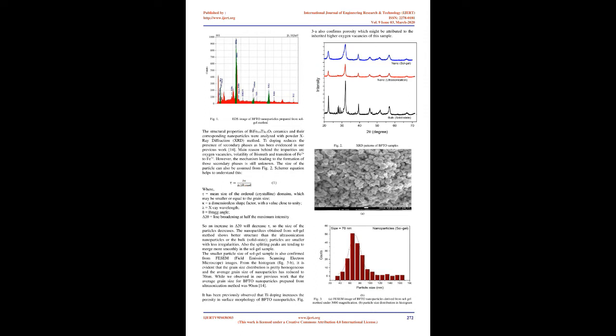Citric acid was also dissolved in 2-methoxyethanol. It acts as a capping agent. Sol-Gel being a bottom-up process, the particles grow larger from atomic scale. When these are small enough, their surface energy is much higher. To reach an equilibrium of energy, the particles tend to agglomerate on the surface. This may reduce the photocatalytic properties of the particles. Citric acid hinders this process.